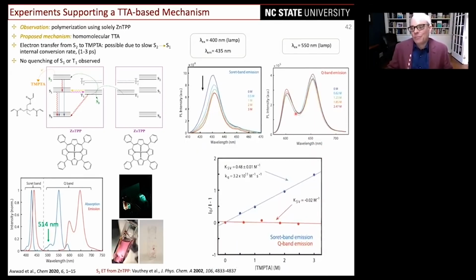We do steady state experiments, Q band fluorescence, no influence whatsoever on the porphyrin concentration. The Soret band fluorescence goes down. The polarity is changing a little bit. That's why the wavelength changes. But in essence, you can see here by steady state measurements too, that we're actually getting quenching of the Soret emission, but really, if anything, anti-quenching in terms of the Q band emission. So this is all coming from the S2 excited state, not from the S1 excited state.